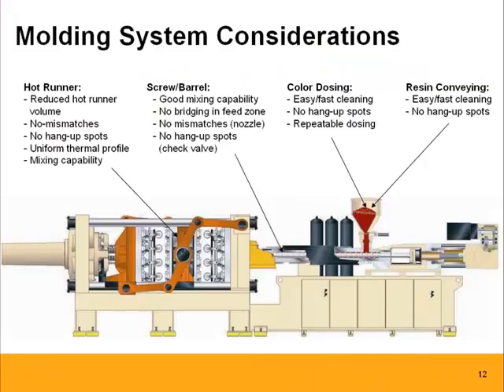So, coming back to a system consideration overall. While we will be talking a little bit more about hot runners and melt flow, I want to stress the point again. You can do all the right things on your hot runner and in your screw and barrel, but very often what's overlooked is what's happening even further up front. So I want to draw your attention to making sure that resin conveying and color dosing can actually be flaws in the system that slow down your color change if you don't properly clean them out, if you created, for whatever reason, hang-up spots in your piping, or if you don't clean the old color properly from your hopper and keep running, start purging, and then you have certain corners or hang-ups because the material wasn't dried properly or something, that material will keep bleeding into the screw and barrel, and of course eventually will end up in your part.